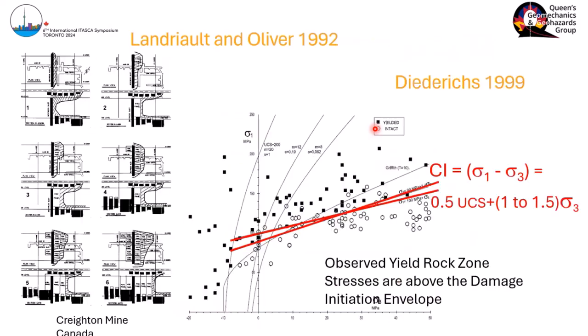And when you analyze that, the black squares are yielded rock masses, and the white are apparently intact rock. What's kind of neat is if you overlay GSI models or intact models, even Griffith, it doesn't seem to work. But if you want to separate this data, you end up with a couple of choices. We originally started saying that sigma 1 minus sigma 3 equals a constant, half UCS. That's not quite right and causes problems. The reality is it's about 50% of UCS plus a slope of about, I use 1.5, of sigma 3. And this seemed to be pretty neat.